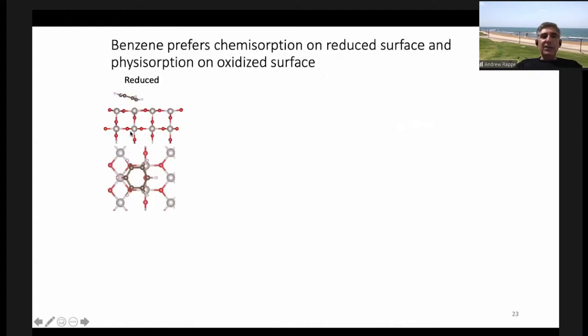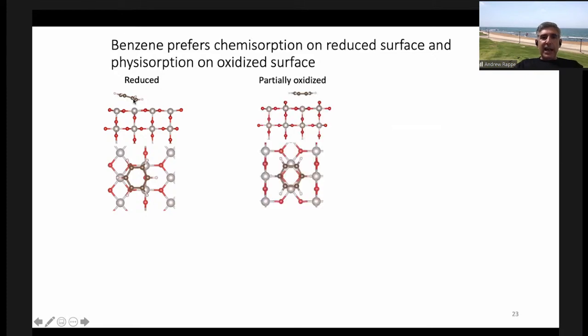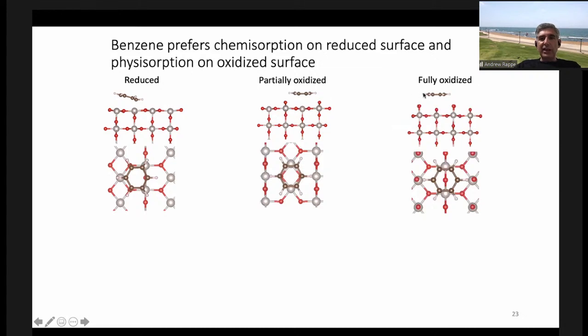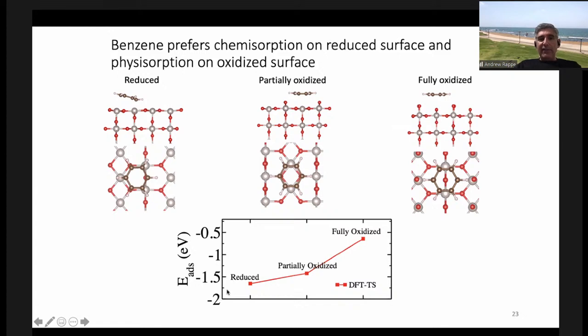Okay, so first we adsorb benzene. And benzene likes to go on the reduced surface, and it bonds less strongly on the oxidized surface. You see how it's flat here? This tilt means it's found a preferential site. Okay, and this is the top view of the benzene on the reduced surface. And in fact, here's what I'm showing you: on the fully oxidized surface, the chemisorption energy is weak, but it bonds more strongly on the reduced surface. Okay, great.